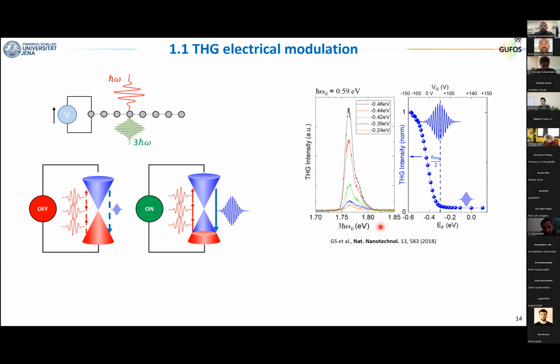And indeed, the materials that are used for nonlinear optics, typically like BBO, KTP, periodically poled, must be fully transparent. So if you want to use a bulk material, you can never go on resonances. And the problem is not for the fundamental photon energy, which is always in the transparent region. The problem is that if you now generate a third harmonic or second harmonic at a certain resonance, and then you propagate inside the crystal, the emitted harmonics will be reabsorbed by the material in a linear fashion. So basically at the output, you will get zero.